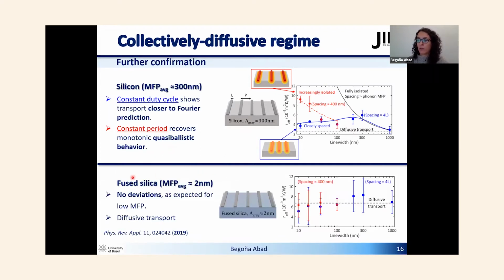Moreover, we did that also with fused silica, whose phonon mean-free path is 2 nanometers, and we saw no deviations. Of course, because the phonon mean-free path is so small that the nanolines and the periods are always larger than this phonon mean-free path, so diffusive transport is expected.